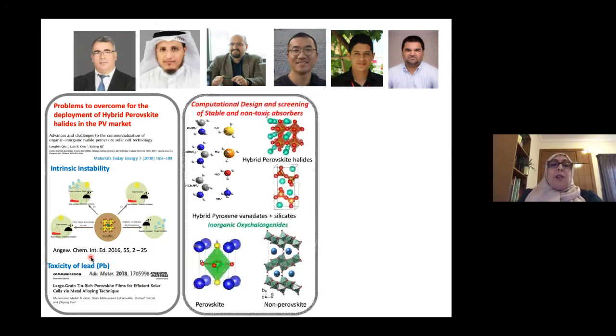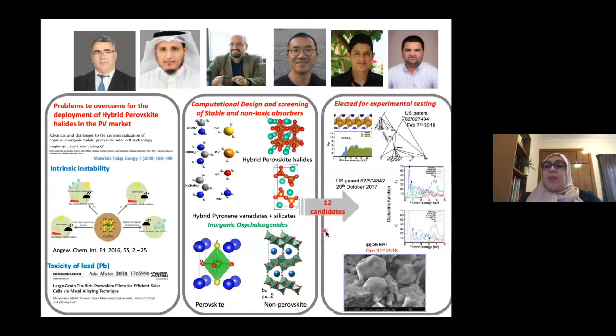What we did is look at different modifications in the materials composition so that we can screen for stable and non-toxic materials. In some cases, we took hybrid perovskite halides and tried to improve their stability. On the other hand, we looked at other classes of materials that are lead-free, like vanadates and niobates and so on. Out of the 3,000 candidates we looked at, we came up with 12 candidates.